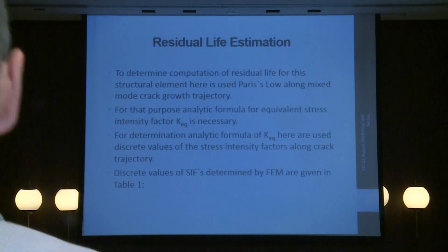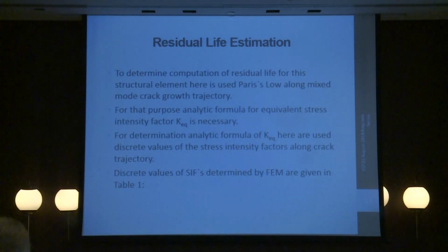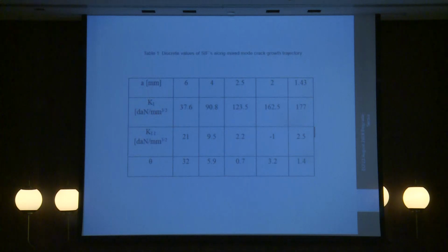For residual life estimation, to determine the computational residual life, the Paris law and the strain energy density method are used. For the analytical formula for the equivalent stress intensity factor, we used the stress intensity factors for mode 1 and mode 2. For determination of the analytical formula, discrete values of stress intensity factors from the finite element method are used, given in the next table for different crack lengths. We have values of stress intensity factors 1 and 2, and of the angle theta.